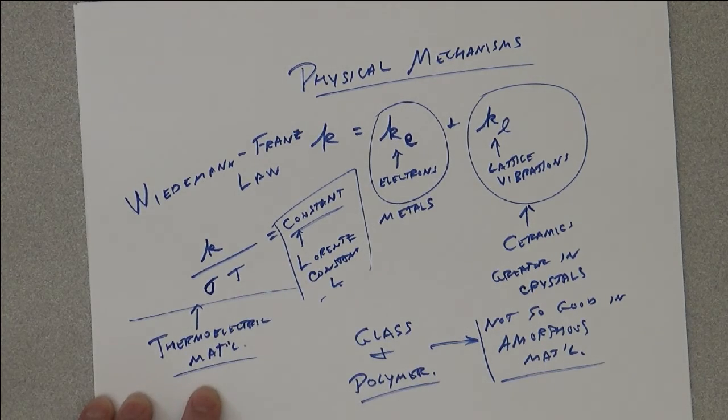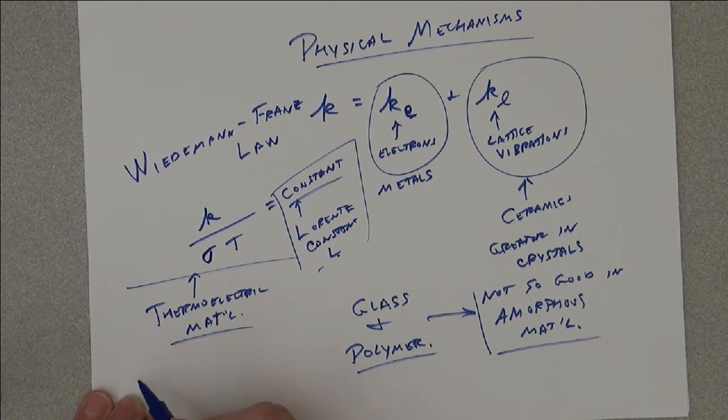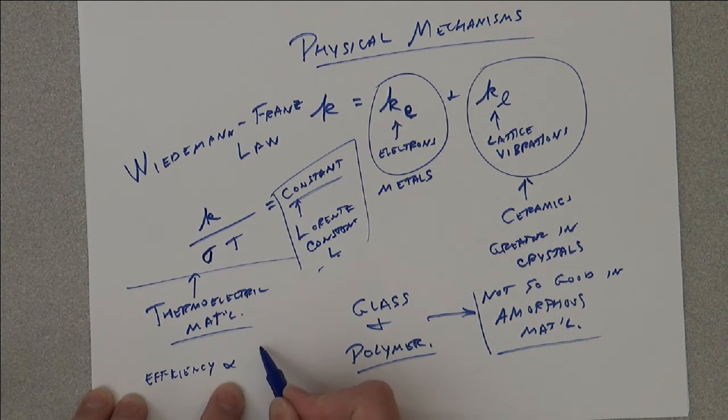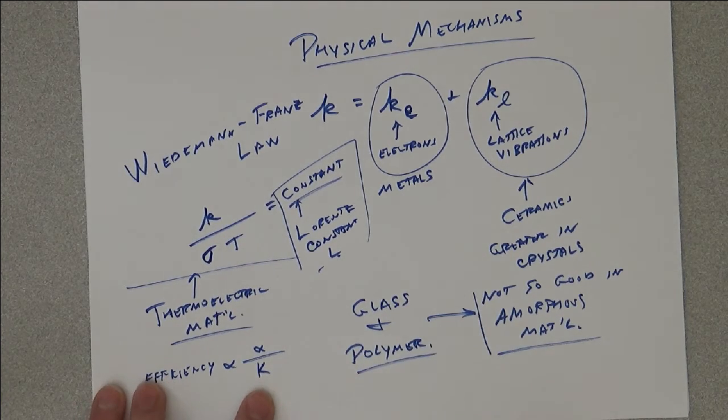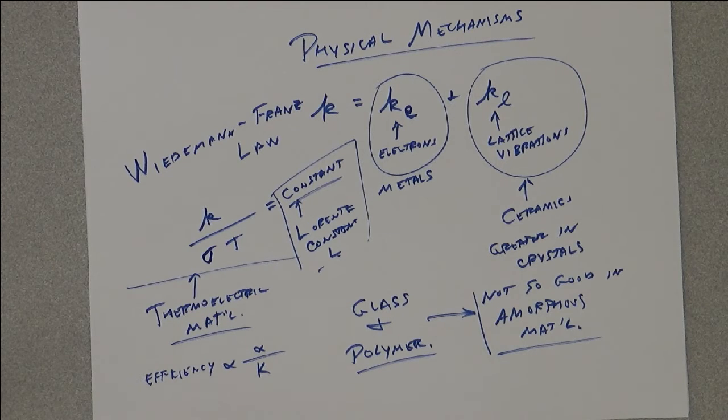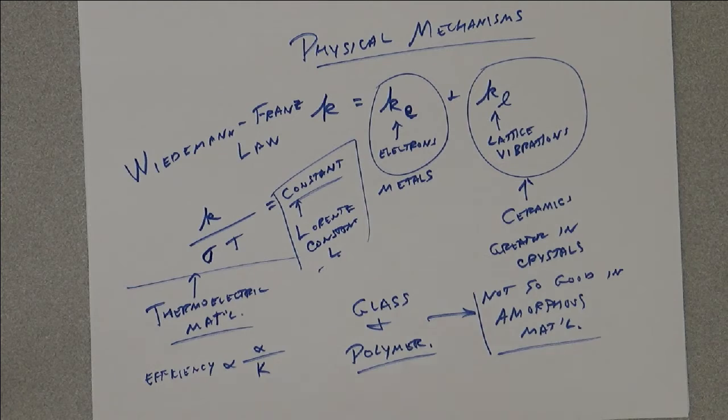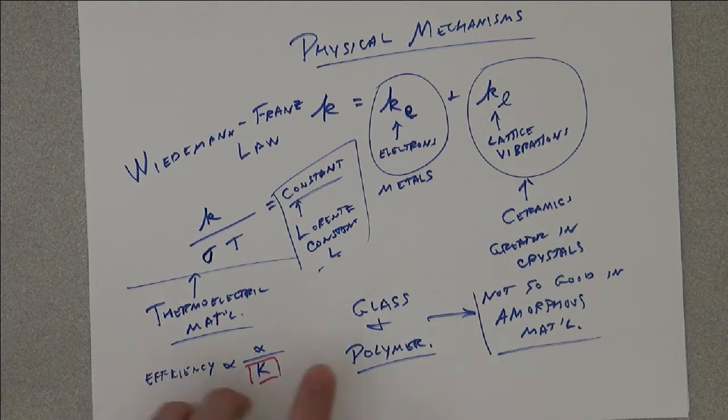Thermoelectric materials is a class of material used to extract waste heat from a process. The efficiency is proportional to the electrical conductivity divided by the thermal conductivity. But because those two are tied together, it's extremely difficult to find good means to make thermoelectric materials. We've been working on these for over 50 years and have made only limited progress. Typically, the game you play is making a kind of okay electrical conductor and then quenching the thermal conductivity by affecting the lattice vibrations.